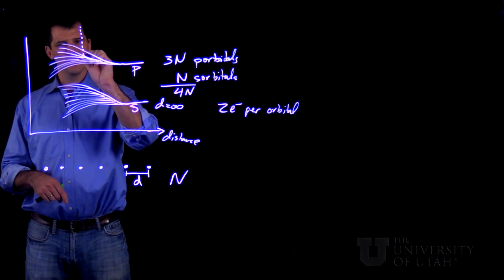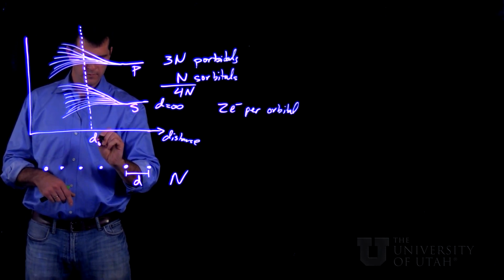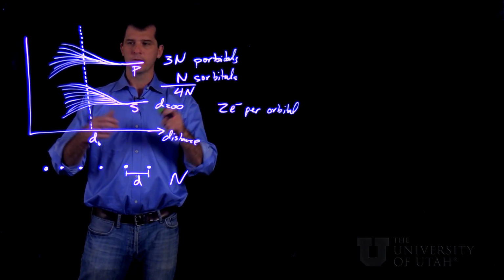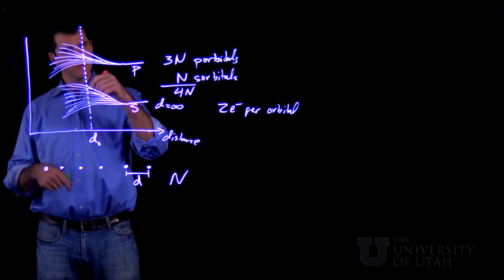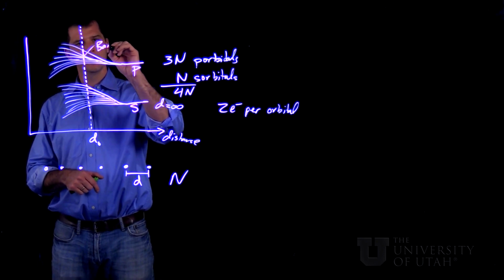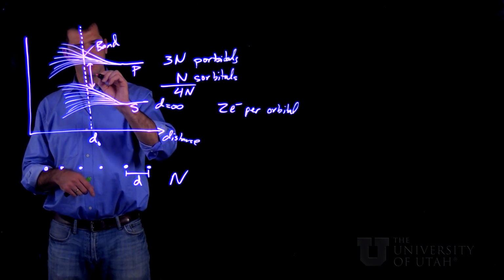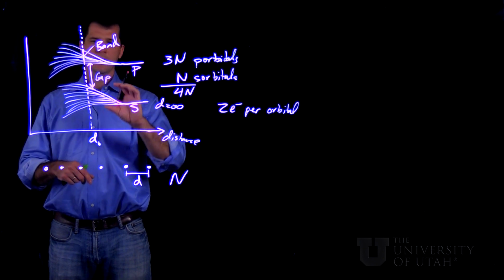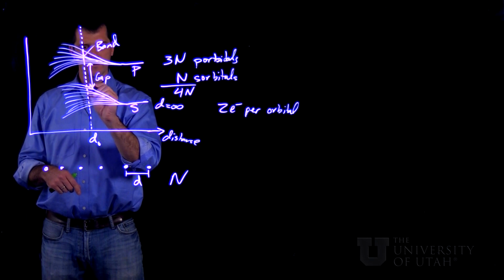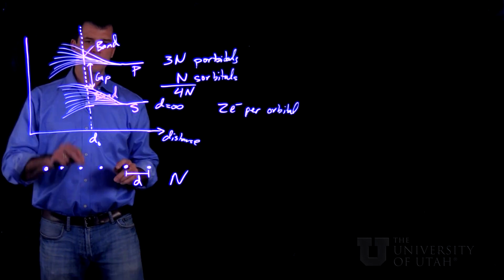So what we have to remember is that in the silicon crystal, the spacing between atoms is fixed because of the lattice constant of the crystal. So schematically, at least, we can see that we have a band of allowed states, a gap between which no solutions to the Schrodinger equation can exist, and then another band of states here.